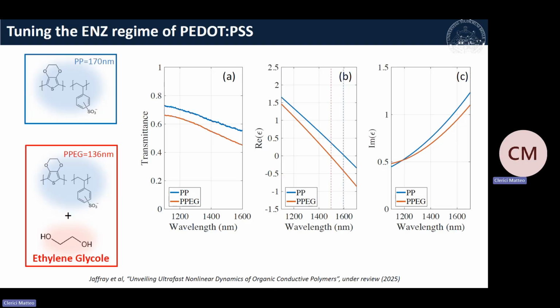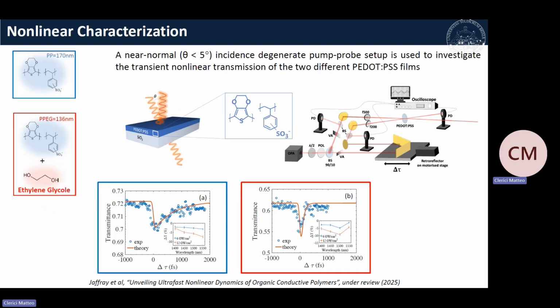So we went ahead and tested the nonlinear properties in this frequency range. We did a near normal pump probe experiment and measured the transmission variation, so the differential transmission, as a function of the delay between the pump and the probe. What we found was that, of course, we do have a modulation of transmission as expected, so we could quantify the nonlinearity of the material. But most importantly, when we switch from the pristine PEDOT to the doped ethylene glycol PEDOT:PSS, we have a dramatic reduction in the time response of the material.